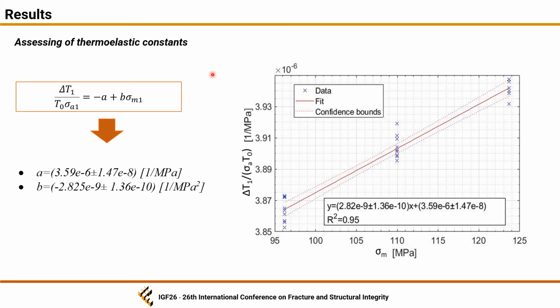In order to assess the thermoelastic constant, a calibration was carried out. The calibration involved the following steps. Firstly, the acquisition with the infrared camera of the thermoelastic signal during a sinusoidal loading test on dog bone samples at different levels of mean load. Secondly, the lock-in analysis and calculation of the first harmonic amplitude and reference temperature T0, and finally evaluation of the thermoelastic parameters A and B by just fitting the experimental data, and we can see the value of this material constant here reported.